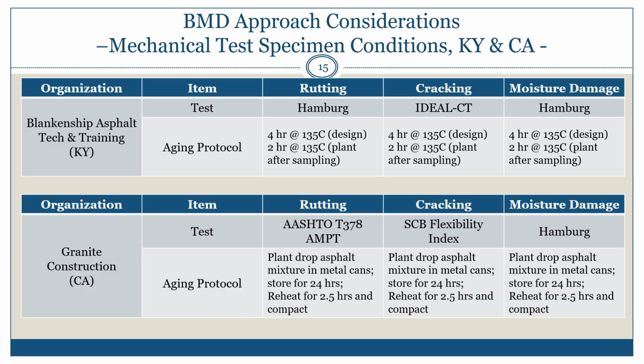Here's two more examples of criteria and specifications that are being utilized for BMD in the states of Kentucky and California. You can see here that they have different aging protocols depending on the test method and how the materials are going to be produced as well, very similar to New York State, but they are using different tests. You can see in Kentucky they're looking to utilize the Hamburg, and depending on whether it's a mix design or plant produced, they have different conditioning levels. They are looking at using the IDEAL-CT for cracking, and again, very similar difference in aging protocols, and also leveraging the Hamburg for moisture damage as well.